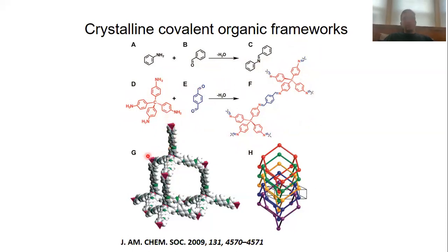the tetrahedral building units. Okay, so these diamond-like networks have also the property that they tend to form interpenetrated structures. So they actually allow the formation of a second diamond network to grow within the first diamond network being formed. And the driving force for that is that nature tends to avoid porosity. Nature tries to fill space as well as possible.